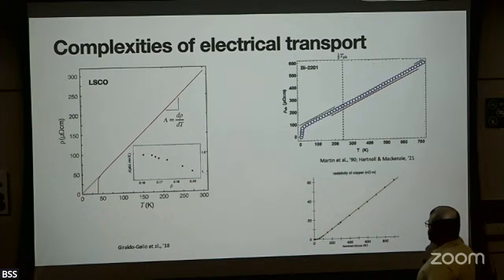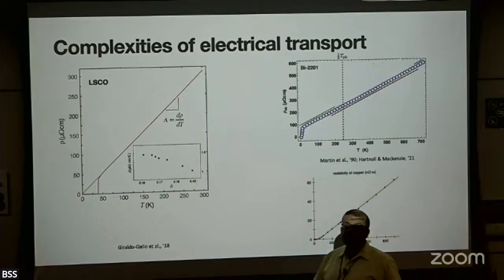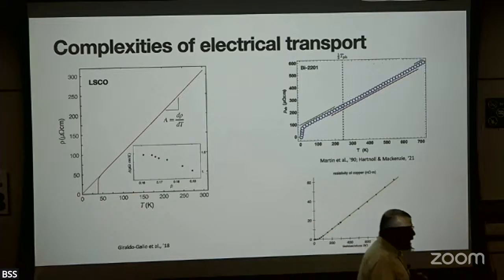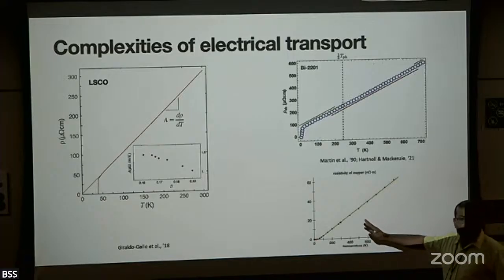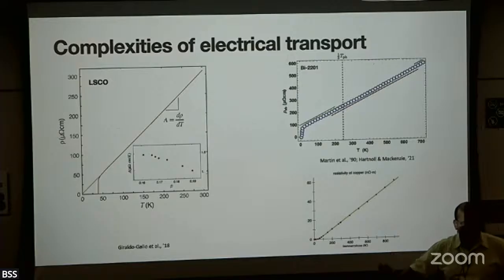Okay, just for reference, this is what the data looks like in copper. You also see T-linear resistivity. Now, interestingly, I was just talking to some students this morning, and it became clear that these days, the moment you see T-linear resistivity, there's a tendency to say, that must be a strange metal. Well, okay, depends to some extent on your definition of strange, but we don't think of this as a strange metal. It's a very well understood mechanism for T-linear resistivity, and we'll talk more about that.